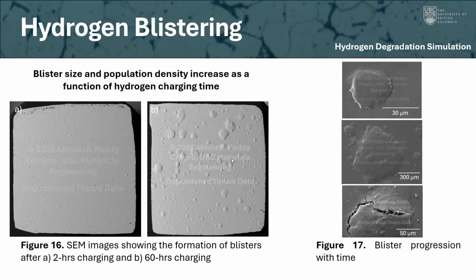And as we can see here are some interesting images. So in figure 16, A and B, A refers to an image that has been charged for 2 hours versus 60 hours. We can see an incredible increase in both the size and the population density of these blisters. In figure 17, we can also see, again, the first image corresponds to the 2-hour charging condition. So we see essentially a lift in the steel matrix. And then as we progressively increase charging, not only do we have these larger blisters, but also smaller blisters concentrating around the initially formed blister. And of course, under severe charging, that's when we start to see severe cracking.